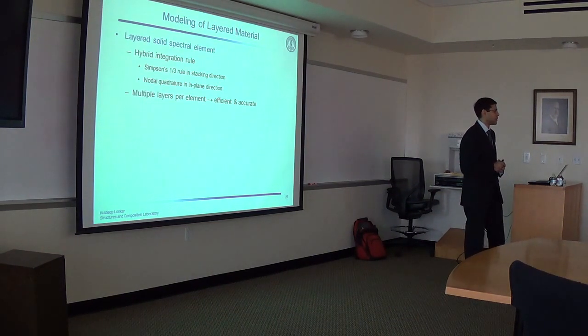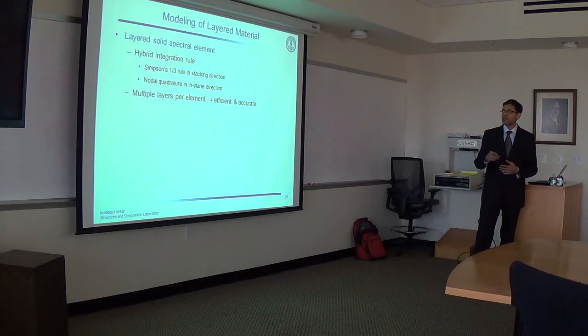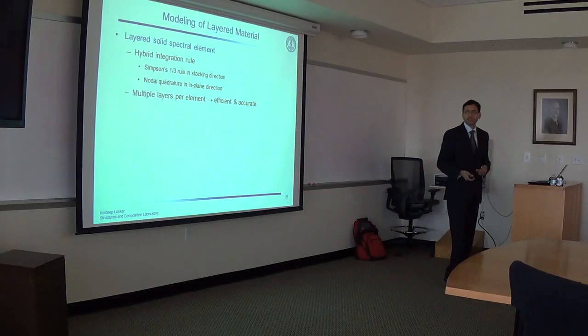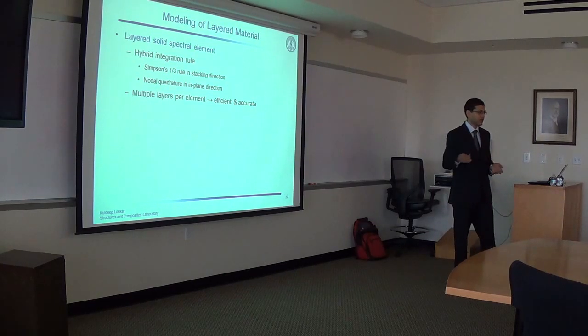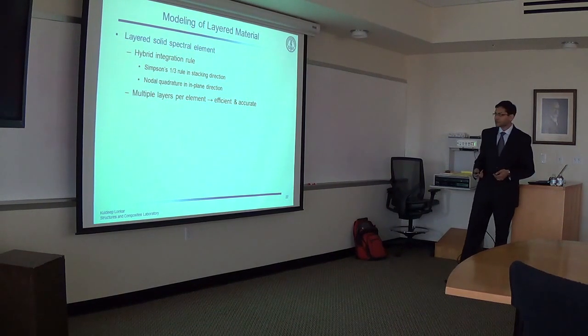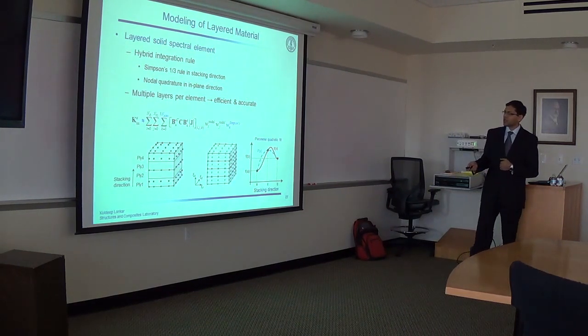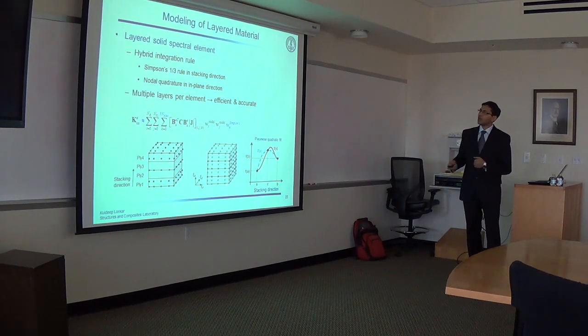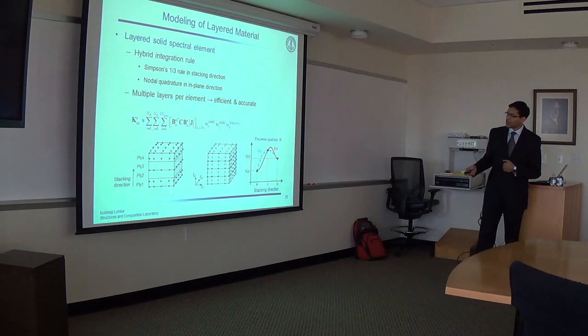the formulation of layered solid spectral element was developed. It uses hybrid integration rule. So basically we use nodal quadrature in the in-plane direction because there is no discontinuity in the in-plane direction. And we use Simpson's one-third rule in the stacking direction. So for example, let's consider the same element again with 4 layers. And these are the integration points of this hybrid integration rule. As you can see, there are 3 integration points in each layer.